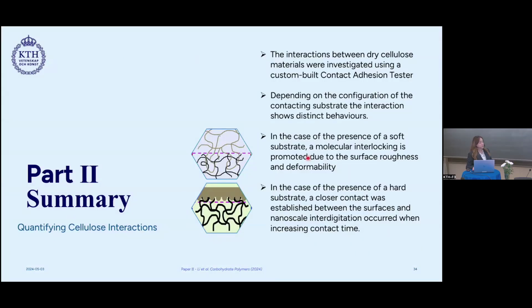So as a summary for part 2, the interactions between dry cellulose materials were investigated using a custom-built contact adhesion tester. Depending on the configuration of the contacting substrate, the interaction shows distinct behaviors, where in the case of the presence of a soft substrate, a molecular interlocking is promoted due to the surface roughness and deformability. And in the case of presence of a hard substrate, a closer contact was established, and the surfaces and nanoscale interdigitation occurred when increasing the contact time between the two materials.